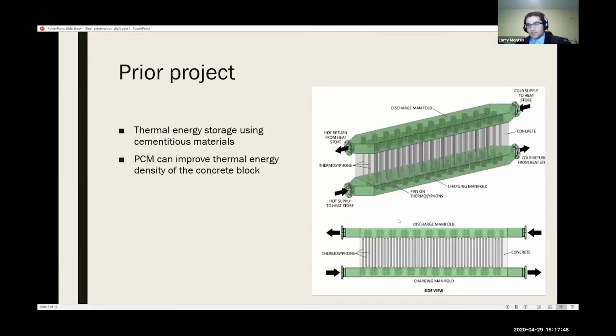In this new project, we are testing the effects of integrating phase change materials into concrete to act as a passive heating and cooling mechanism. While this current project focuses on using PCM concrete in room temperature settings, the potential for this study is implementing PCM in the thermal energy storage system concrete, as a PCM with a phase change temperature around a power plant's operating temperature would allow this storage system to absorb much more thermal energy per unit volume and increase storage capacity.